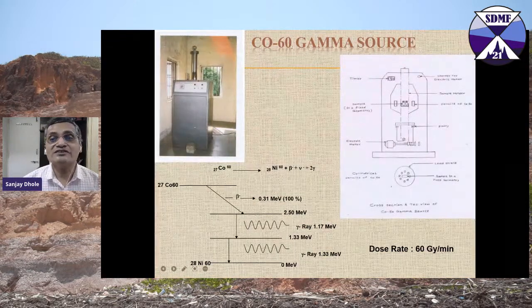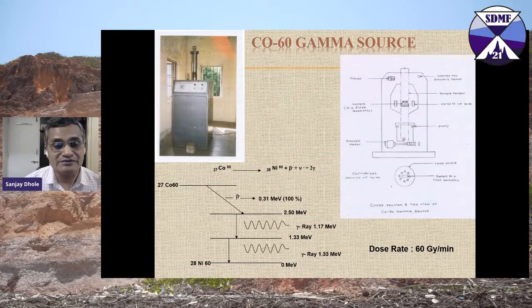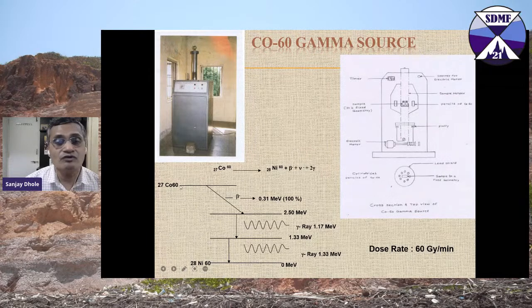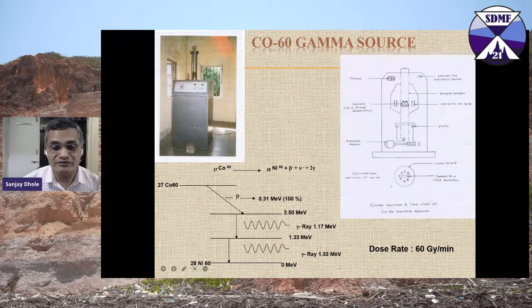So this is the Cobalt-60 gamma source, which is available on the campus. It is with us only. As you know, if you see the decay scheme of Cobalt-60, it decays by beta, and then subsequently de-excites from this level to this level. Then there are two gammas coming out of it, 1.17 MeV and 1.33 MeV. The dose rate of this particular gamma source is 60 gray per minute.